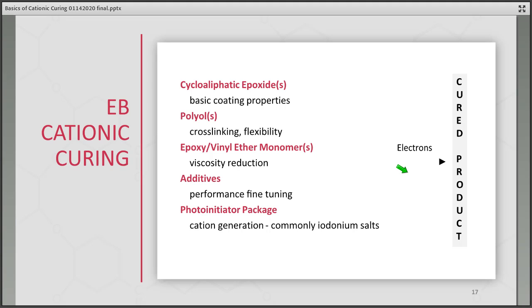Something that's a little bit different in cationic cure than it is in free radical cure is that you can cure these systems by electron beam, so EB curing. However, a big difference, and this tends to sometimes surprise people, is that while a typical formulation may look the same through the cycloaliphatic epoxides, polyols, additives, etc., to cure cationic systems by EB, you need a photoinitiator package because you can't generate cations using the electron beam. So you have an initiator that will break apart. These are commonly iodonium salts, and you'll then generate your cation, and you get cationic cure through exposure to EB, and you get your cured product.